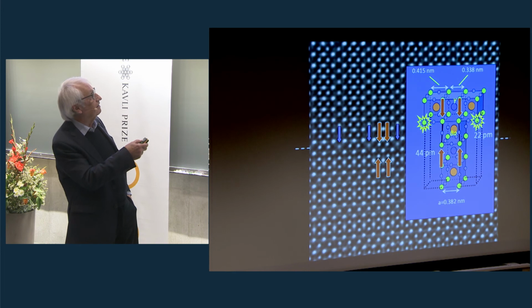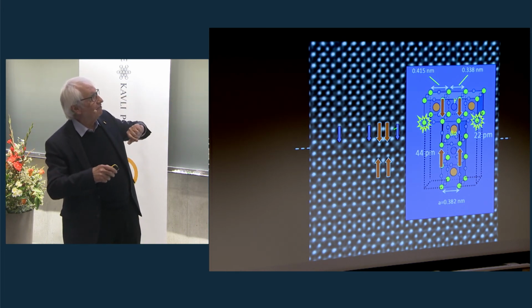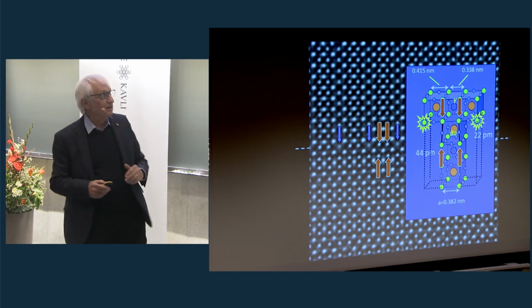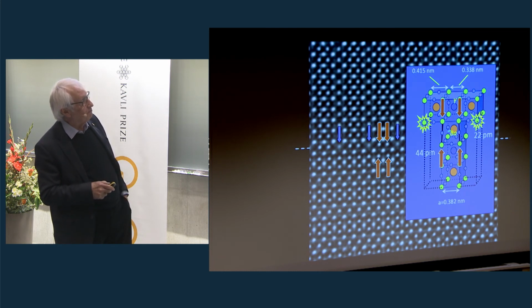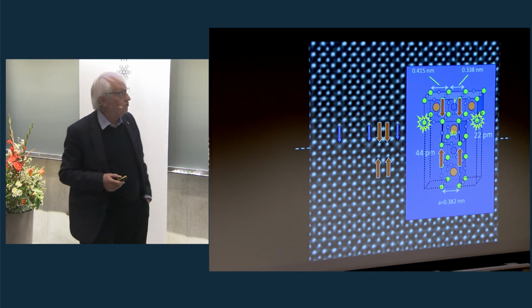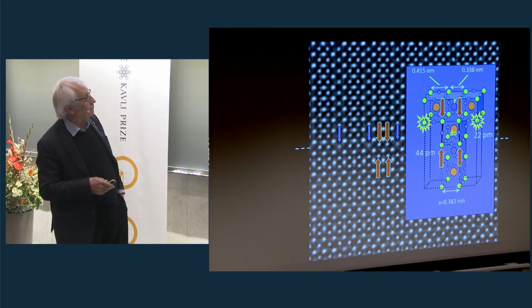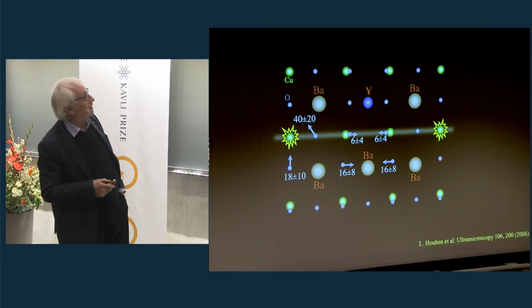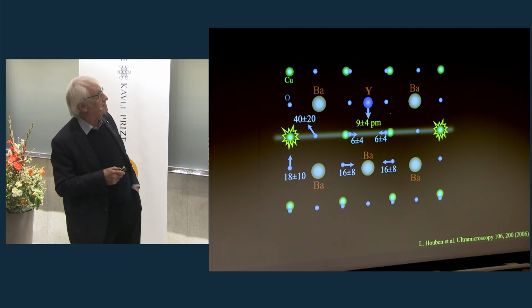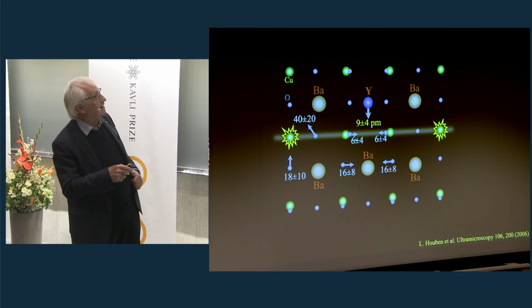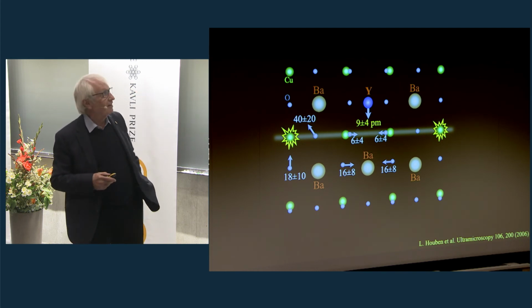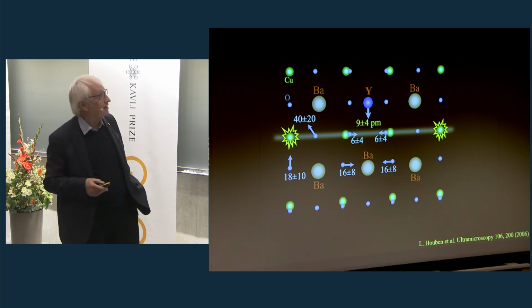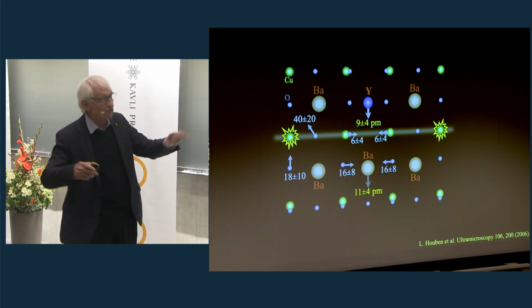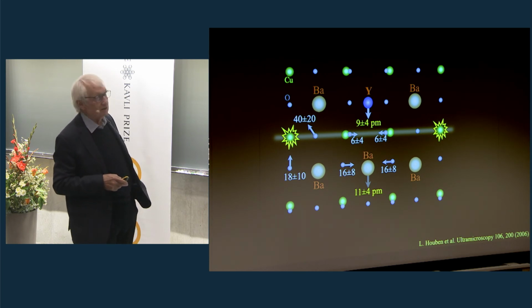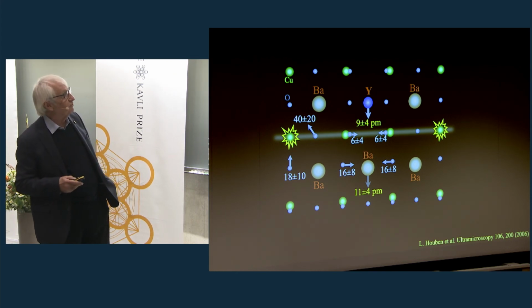And since a lying unit cell of yttrium, barium, copper oxide does not have the same lateral dimensions as 3 upright standing unit cells, we have problems here. We have a misfit, and the misfit has electronic consequences. You also have changes in contrast here. I don't want to go into detail here, and I show you one of the earlier measurements we have done on this, and here I only concentrate on 2 atoms. The yttrium atom is small. It's pushed into the grain boundary by 9 picometers. Since it's an early measurement, at that time the measurement precision was only 4 picometers. We can do better today. And the big barium is pushed out of the boundary by 11 picometers.